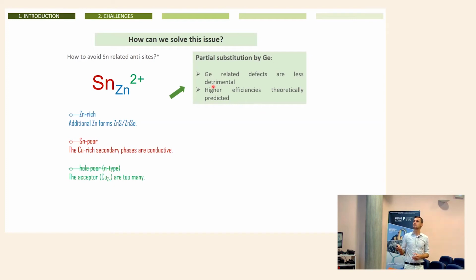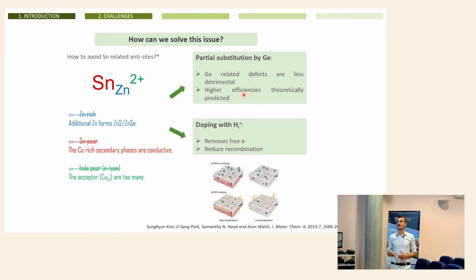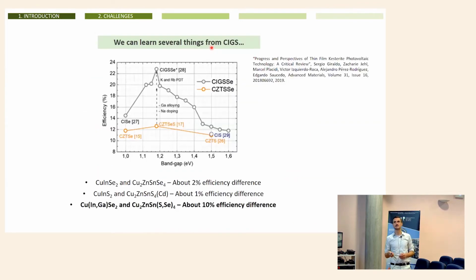So the possible solutions we are investigating. First is the partial substitution of tin by germanium. Germanium is a more novel material in the sense that normally the defects are less detrimental, at least from theoretical investigation, and higher efficiencies were also theoretically predicted. The second is doping with hydrogen, basically inspired by III-V semiconductors. In them, the doping with hydrogen normally removes free electrons and reduces recombination. And I will show you the latest results about all this doping and alloying on kesterite. These are just two examples.